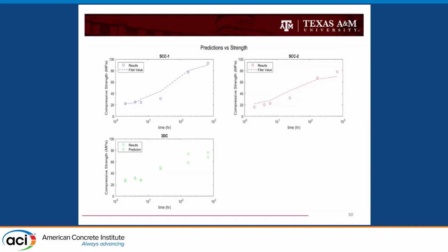So we wanted high early strengths, but we wanted to make sure that this mineral admixture was not staggering the strength development from the cement. We want to make sure that if you're forming these ettringite crystals, they are small enough that they will still give space for CSH growth. And this is basically what we tracked for the 3D printing mix, and the same for the self-consolidating ones.